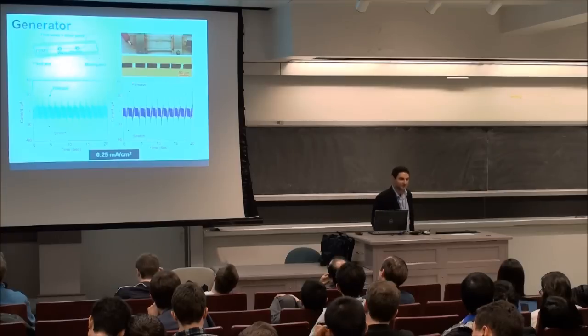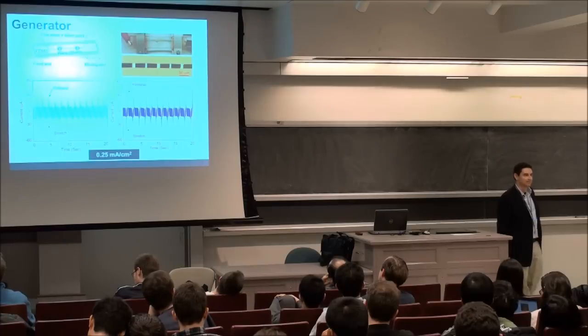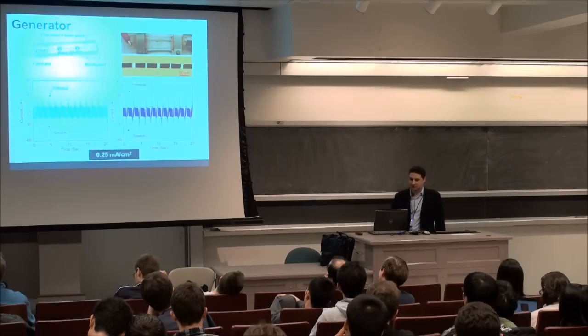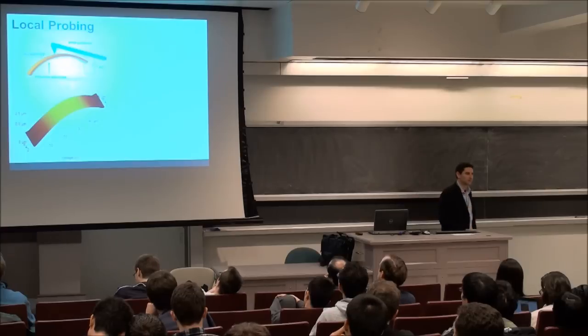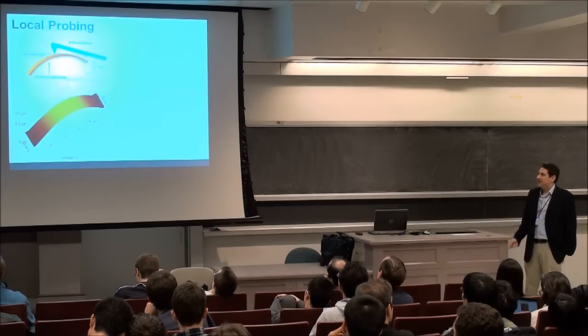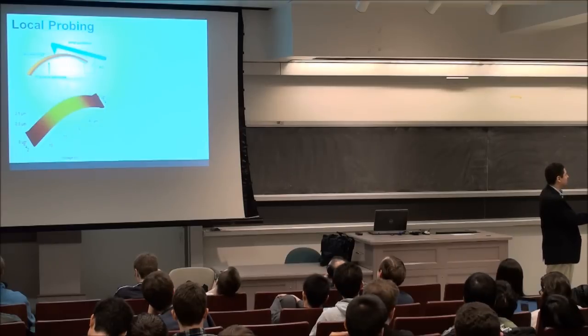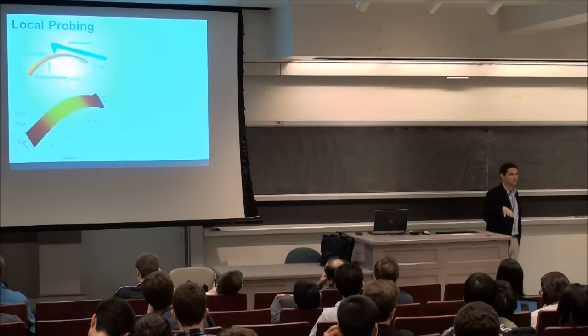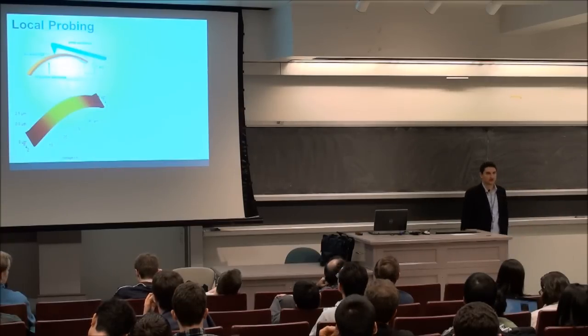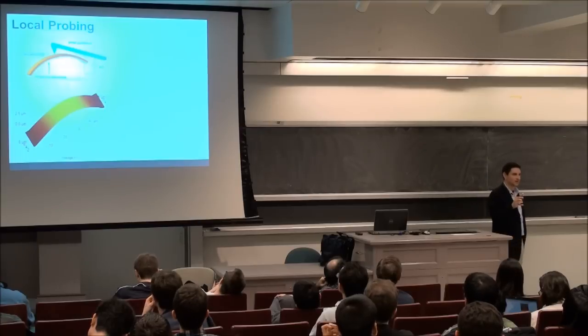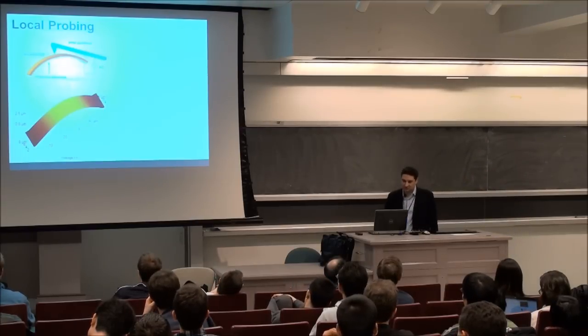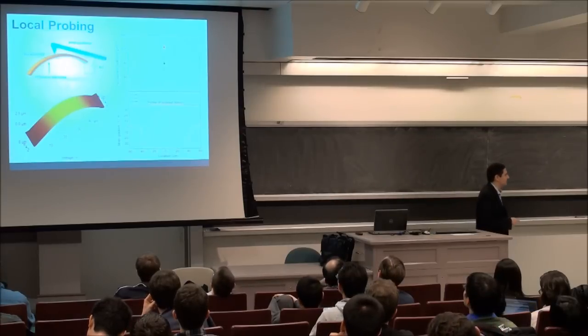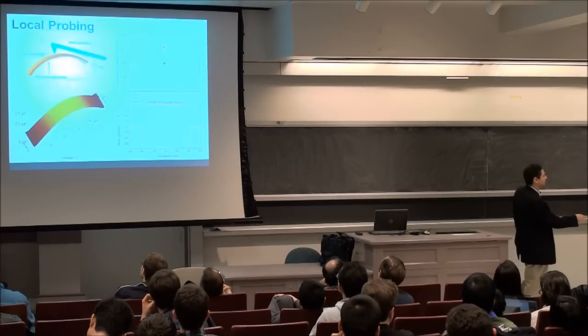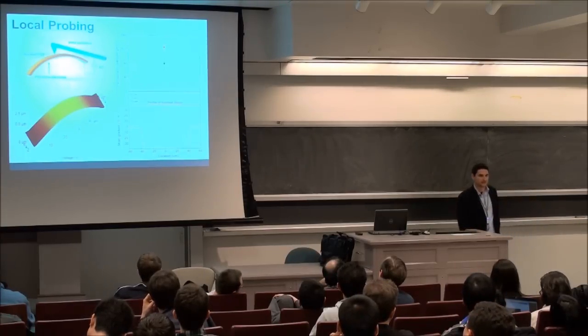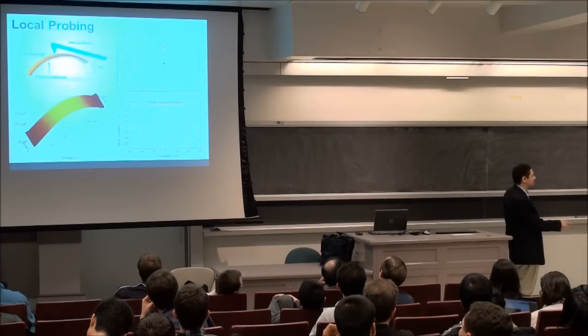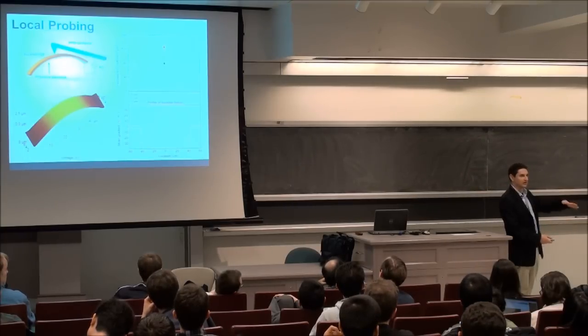But what we thought was incredibly fascinating as we did this, something that we were somewhat surprised about, is we looked at what's actually going on in the ribbon locally using our PFM probe, this piezo force microscopy probe. It's a nanometer probe, so you can probe the top of the ribbon and you can probe the flat part of the same ribbon. So here's the AFM image of what that buckle looks like. And we wanted to see if there are any differences in the piezo response at the buckle versus the flat part. Okay, and we saw this really cool result here, where as you go from the flat part of the ribbon up to the buckle, you actually get a 50% enhancement in the D33 value. So you actually get an enhanced piezoelectric charge constant due to this buckling of the ribbon.